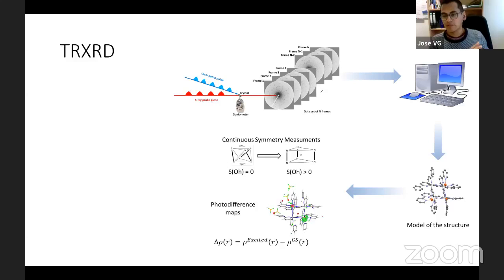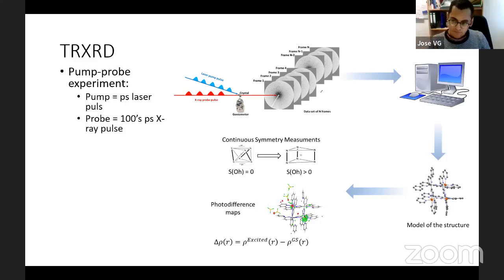So we can take that first in the dark before the laser excitation and after laser excitation, and then we can compare the structural changes before and after laser irradiation. And of course, the difference in time between the laser and the X-ray pulse will give you the time of the picture. So the picture will be taken hundreds of picoseconds after laser irradiation, or could be taken a few nanoseconds, a few microseconds, or a few milliseconds after the light irradiation.